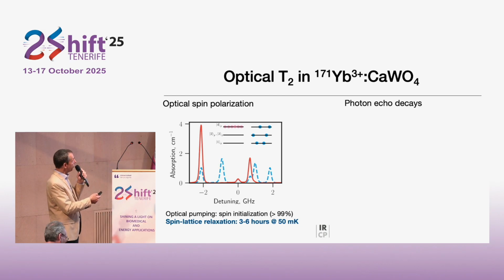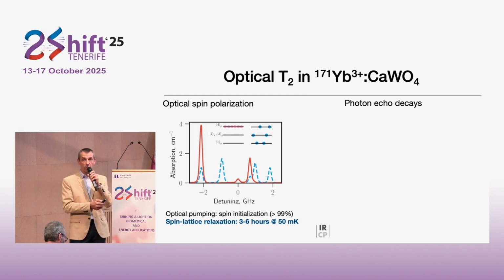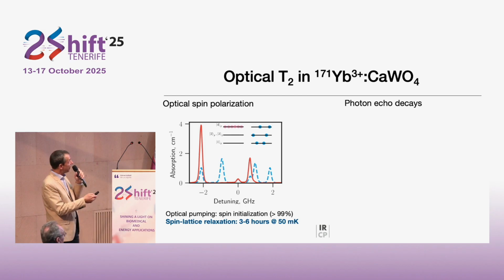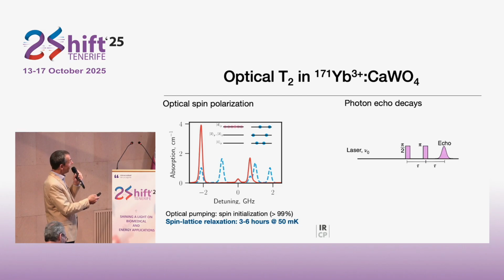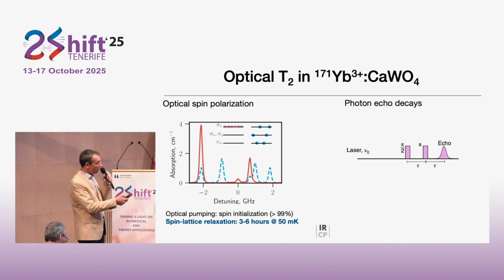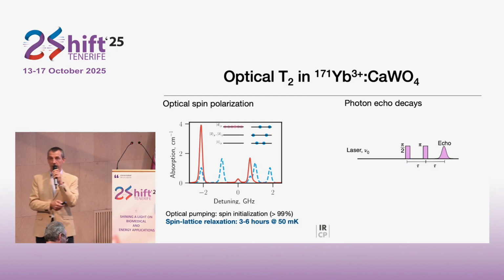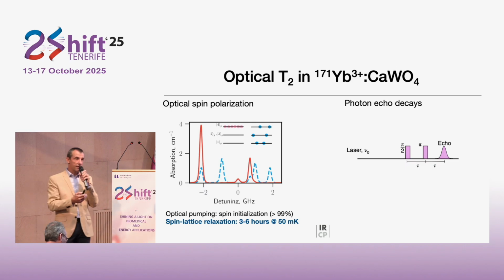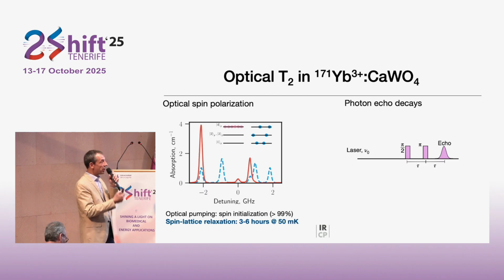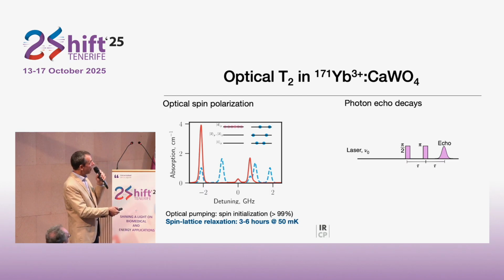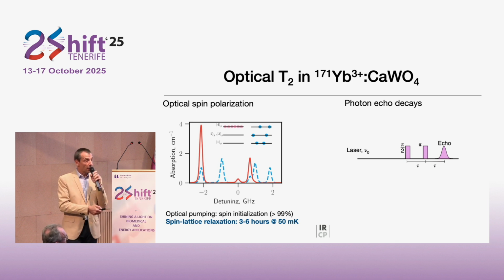Okay, now we turn to measurement of the quantum state lifetime. We use for that a technique which is called the photon echo. Very nice technique, which is relatively simple. We shine a first laser pulse on the system. This light is absorbed by ytterbium ions. This creates optical quantum states. After the pulse, they evolve freely during a delay tau.